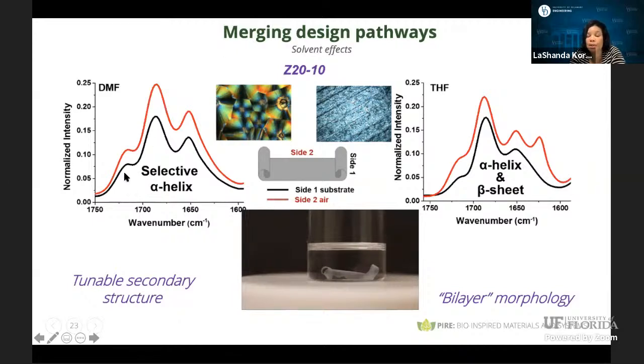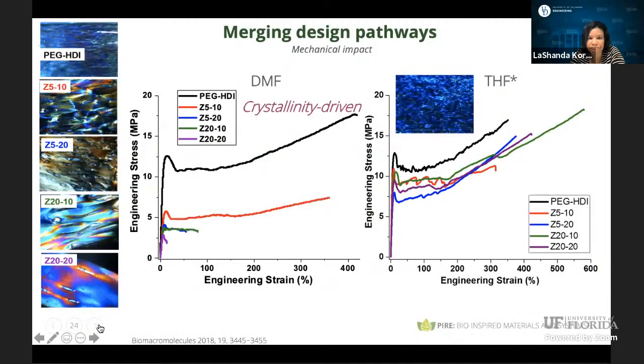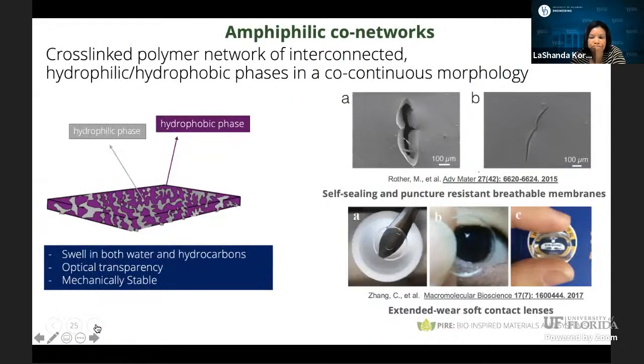And we've shown that depending on the secondary structure, you get very different mechanical properties of these systems. Here it just shows that mechanical impact with DMF, it's all crystallinity driven. In THF, it's a mixture. So you have very similar moduli of these material systems. So there's an impact overall on how we can use this to drive mechanical behavior.